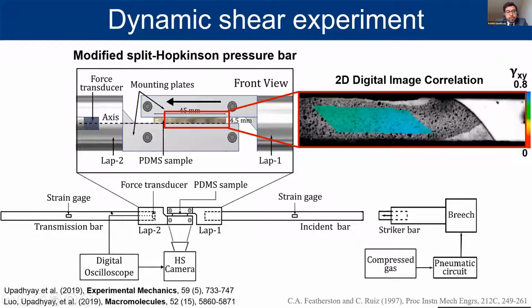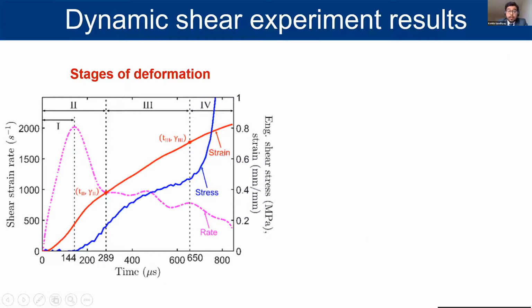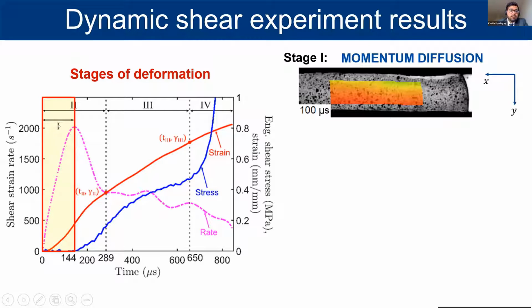By using the force and stress signal from the force transducer and strain rate from the 2D DIC, we make what is called the master curve. In this curve, the magenta line shows the strain rate versus time response, the red line shows the strain versus time, and the blue line shows the stress versus time. The idea of this master curve is a major contribution of my work because it allows the delineation of the different stages of deformation. I call the first stage momentum diffusion because in this stage, the shear momentum is being transferred between the two lap plates.